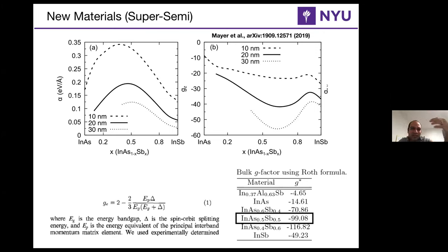On the other side, if you're looking at the Rashba spin orbit, it's the opposite effect, right? If you go to the left graph, you will see that for a 10 nanometer well, you have such a confinement at the surface that it gives you a very strong Rashba parameter. How does the Dresselhaus play a role here? We actually include it, and then we just do a K-linear fit around the gamma point. I'm not sure how well that captures it. That I will leave for the theory. But definitely you don't get the G factor that we want when we usually make a quantum well